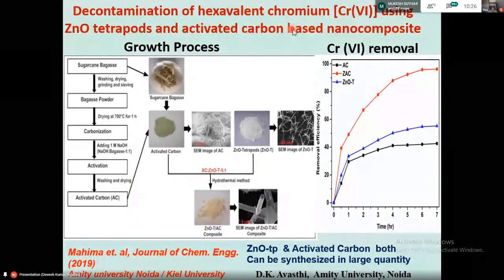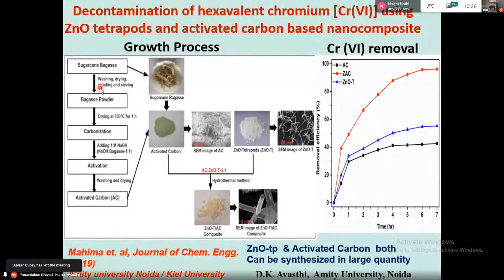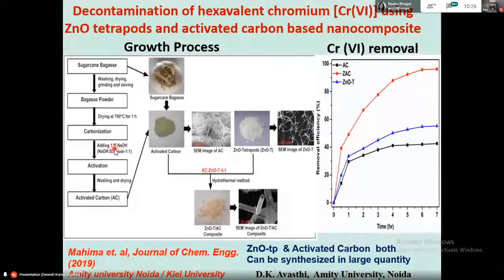How this activated carbon is made, the steps are here. The sugarcane bagasse is a waste material from the sugarcane industry. So one can dry it and grind it, and then you get bagasse powder. Then it is heated at 700 degrees centigrade for 1 hour. Carbonization occurs, and then you add a certain amount of NaOH, and there is activation of it, and after washing and drying, you get activated carbon. So this is a picture of activated carbon, and this is a picture of sugarcane bagasse, you can see, and this is the SEM image.